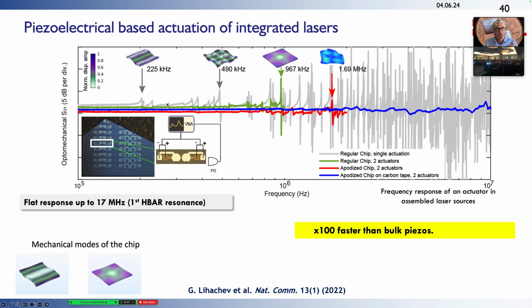But when we start to play tricks like apodization, which is also used in wireless technology, out of phase driving, or just clamping the chip down, we can create, as shown in blue, an exceptionally flat bandwidth up to the first H-bar mode, the first bulk acoustic mode of the actuator. That's typically at 17 megahertz. To compare this with bulk lasers, this is about a factor of 100 times faster tuning. So what we have here is a really unique combination of very fast tuning and exceptionally narrow linewidth.